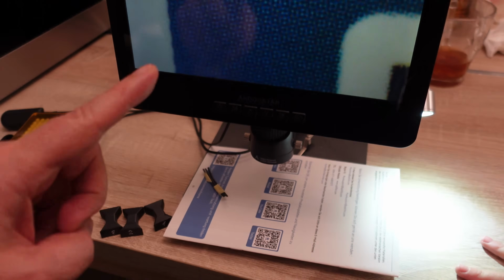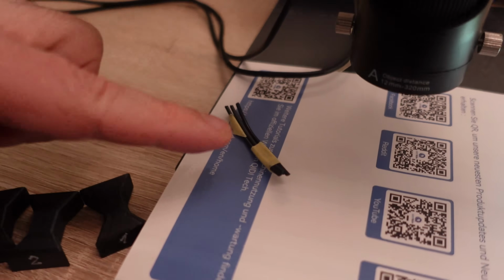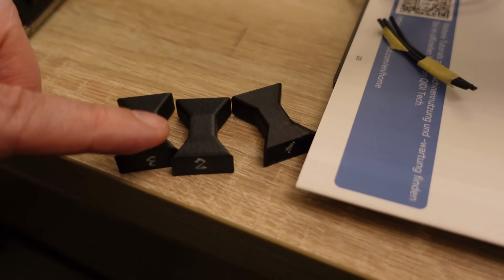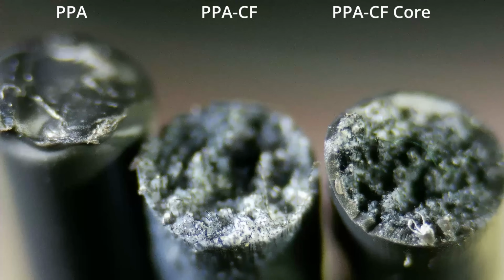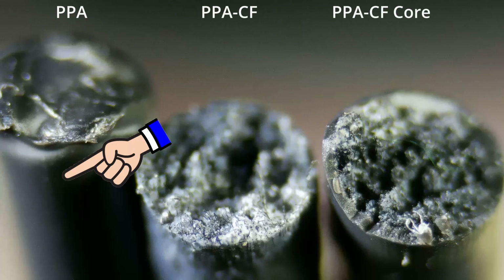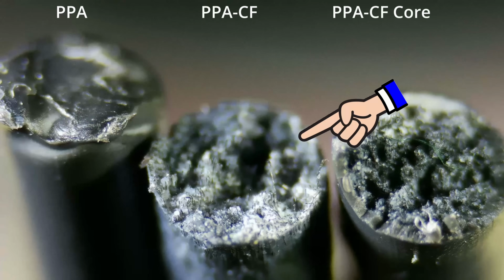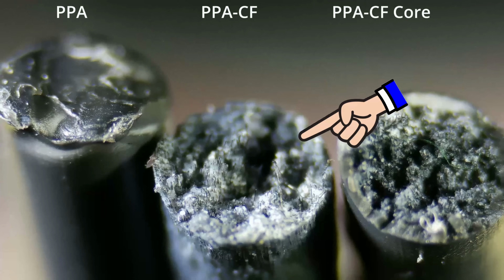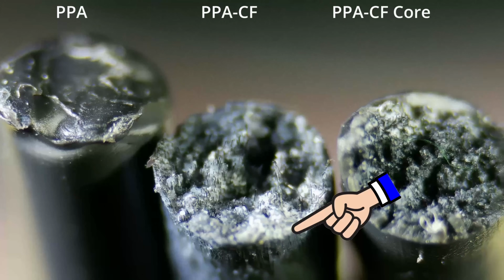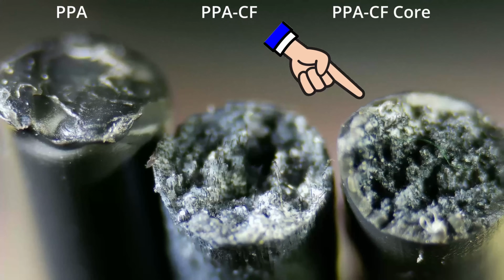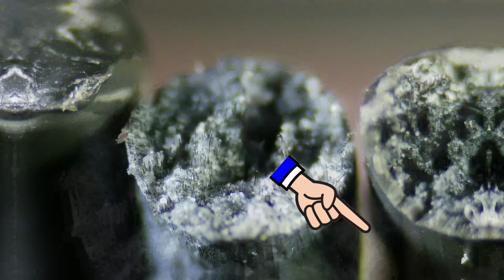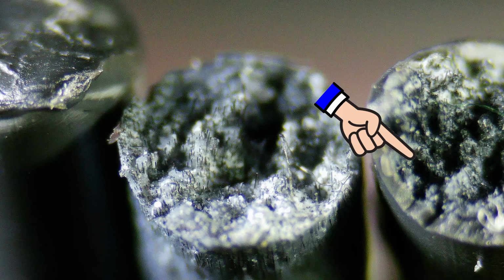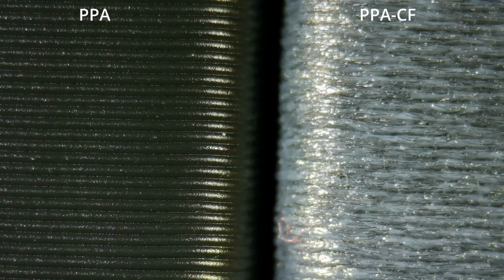Let's check what we can see under the microscope, and first I will start with the filaments and then with the printed objects. So these are filaments, and for PPA we can see that it is smooth outside and inside. In the middle is the CF carbon fiber version, and we can see those fibers even on the edge. And the core version, it looks like it works because outside it is smooth and somewhere here inside we can see those carbon fibers.